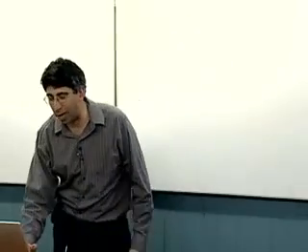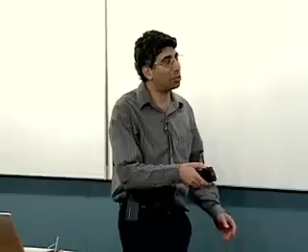Yes? Yeah, so the kinetic term you're talking about is basically on the front of the layer, the reaction with the... In this case, it is the outer layer, yeah. An ion comes up, it hits it. As soon as it hits it, it's getting oxidized or reduced, reduced in this case. Right. But I mean, it could have turned out that any of these processes were rate limiting, and then that's what we would have learned about. But it turns out that in that particular case, it is this process right here that is the rate limiting process. And so that's what let us relate it back to the Marcus theory. So in other cases, it will have a different equation.